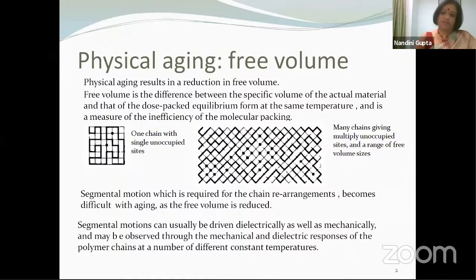Now, the first aspect of aging is, of course, the physical aging of any material. The most important effect of physical aging is a reduction in free volume. Now, what is free volume? This is something that we don't really talk about. Essentially, when we're talking about solid dielectrics, there is an equilibrium status of the molecules of the lattice structure such that the material would have a particular volume. And in reality, that does not happen, and free volume is the difference between the specific volume of the actual material and that of the close packed equilibrium form at the same temperature.